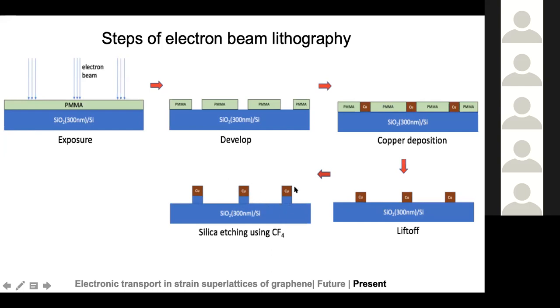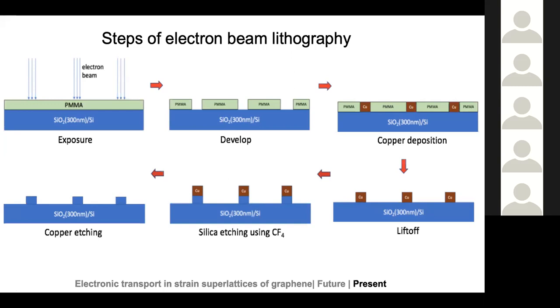So all those regions which had copper on top will be masked and will remain. And once we have removed the copper using ammonium persulfate, we'll be left with whatever features we wanted on the silicon dioxide layer. So all we wanted was a set of ridges, right? It was a very simple procedure to think of in principle, but it's much more difficult in practice.